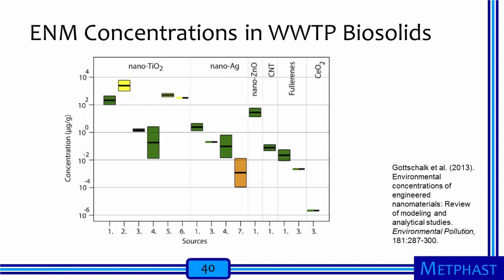several studies. The one study that looked at nanozinc oxide suggested concentrations between 10 and 100 micrograms per gram of biosolid. Concentrations for nanosilver were all below 10 micrograms per gram, while concentrations for carbon nanotubes, fullerenes, and cerium oxide nanoparticles were lower than 100 nanograms per gram.